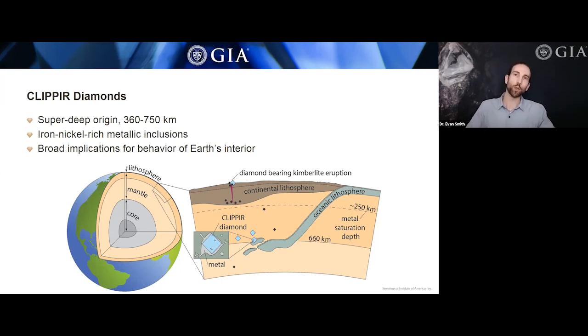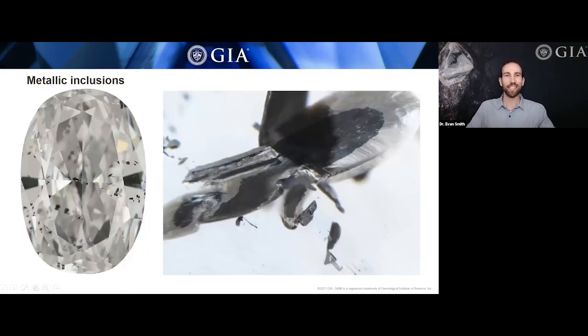So the main inclusion we find in these diamonds is stuff like this, these metallic inclusions. And on the scale of the faceted gemstone, these often look like little black specks, but under higher magnification under the microscope, we can see these shiny, silvery looking shapes that are actually metallic in composition. They're actually rich in iron and nickel. And on the next slide, I can show you a cross section through this inclusion here, and we can see what it looks like inside.